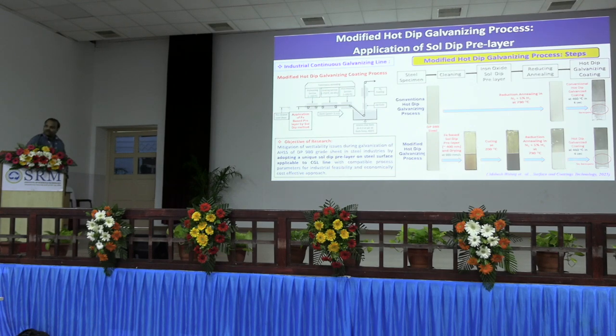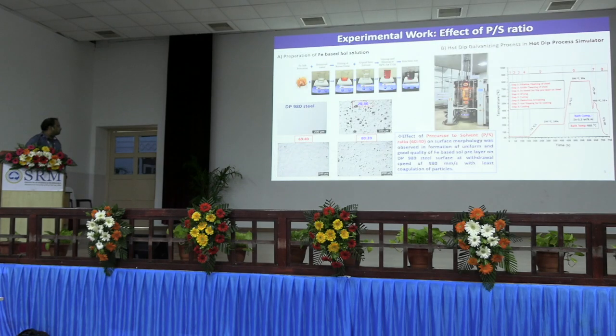And this metallic Fe layer will improve the reactivity of the molten zinc on the steel surface, and we will get a uniform coating without any uncoated spots. For this, we prepared the iron based sol solution using an iron salt precursor, and the precursor to solvent ratio was optimized to get a uniform sol dip pre-layer. Then the steel sheet coated with the sol dip pre-layer was simulated for the continuous galvanizing process in a hot dip process simulator, which is a very unique facility at the CSIR-NML.